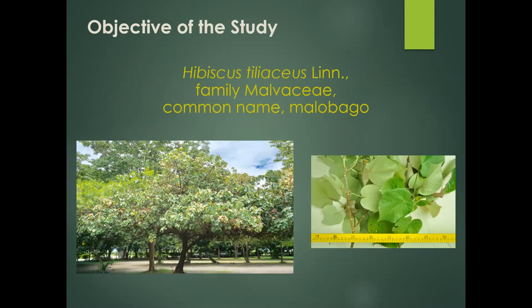As reported in various papers in literature, the ability of plant leaf surfaces to exhibit a wide array of unique characteristics may be partly attributed to the nature of its structures. There has been growing interest to better correlate plant leaf surface topography and the resulting properties. Studies in this area are important as they can provide a better understanding of the potential biomimetic applications of plants. It is the aim of this work to study Hibiscus tiliaceus Linn for this purpose. Previous data from our work already revealed a promising application based on the measured high sorption capacity of 1.7693 ± 0.0793 grams of oil adsorbed per gram sorbent of the plant's leaf, and this provided an inspiration to study other aspects of the plant leaf.